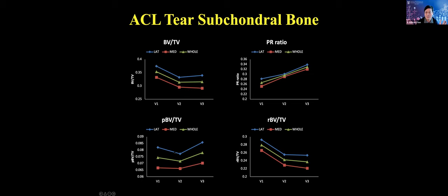And then indeed, as observed here using this technique, we identify that you lose rods initially, and also the plate-rod ratio has changed. So therefore, we have some evidence suggesting those early changes, even though very subtle, are actually causing fundamental structural changes in here.